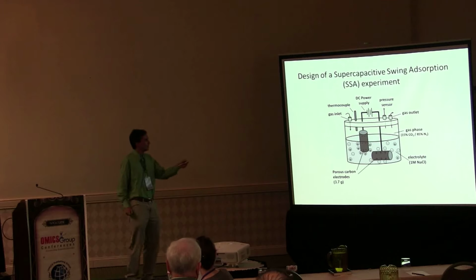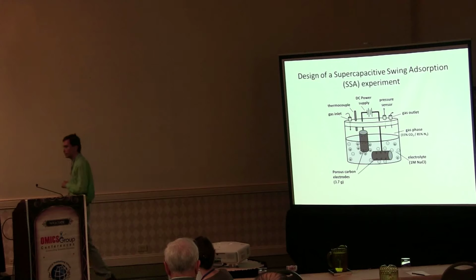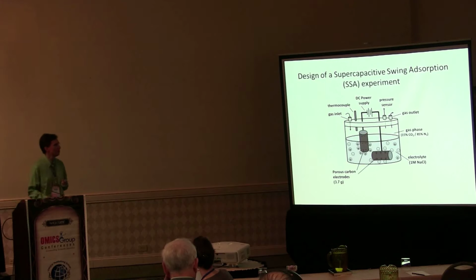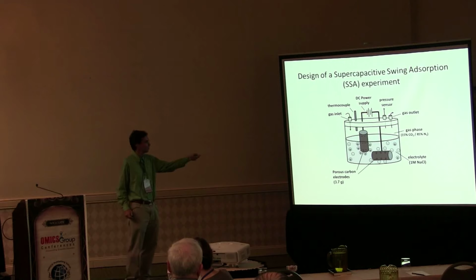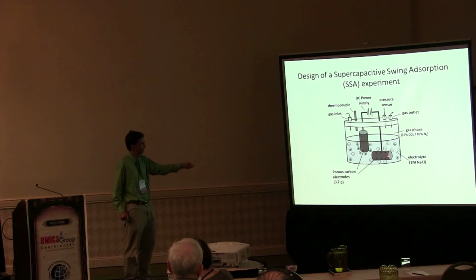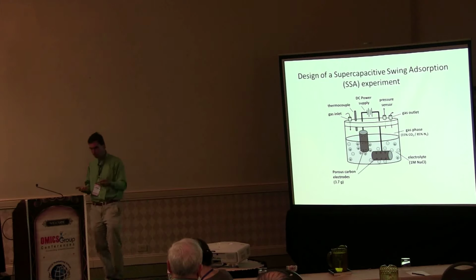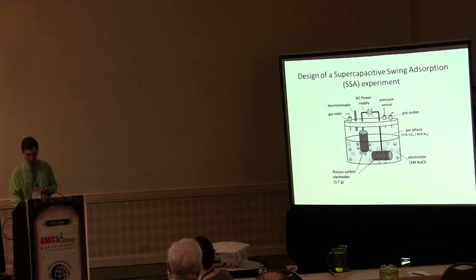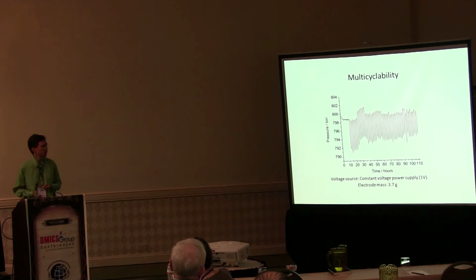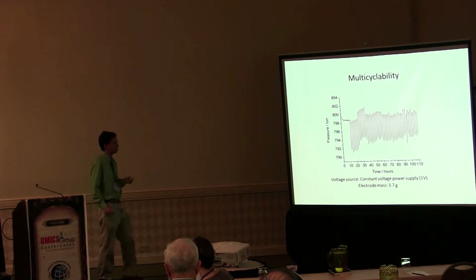Furthermore, you see here a pressure sensor is attached. This pressure sensor senses possible adsorption as we apply a voltage with a DC power supply to our carbon electrodes. So if there is a significant adsorption occurring, the pressure should change. Now we have measured the pressure inside our gas adsorption cell as a function of the applied voltage, and you see the result here.